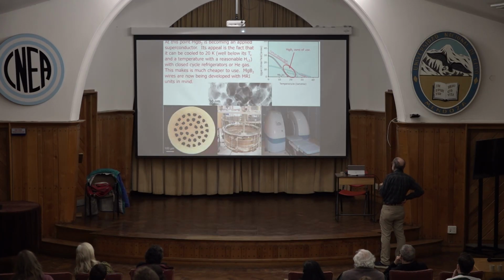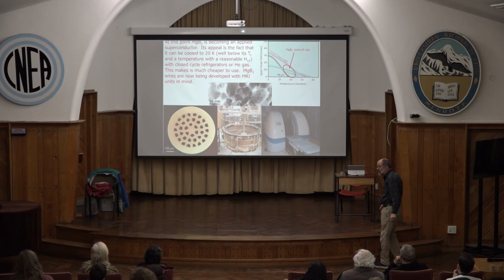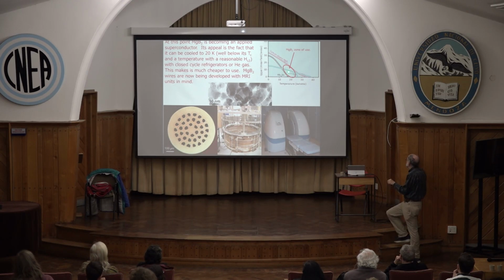And in the past 25 years, this 20 Kelvin here has become known as the MgB2 zone of use. 20 Kelvin, niobium 3-tin doesn't superconduct. At 20 Kelvin, we can have HC2s of 15 Tesla. Not bad. And 20 Kelvin means you don't need to use liquid helium. You can use cold helium gas cooled by a closed-cycle refrigerator.